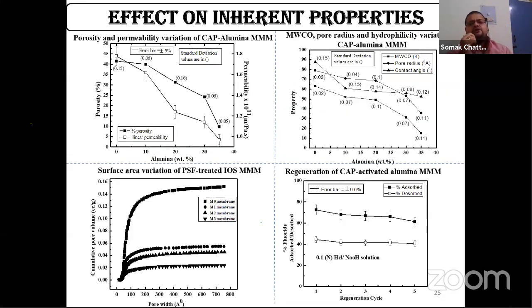Now, different inherent properties were also significantly impacted. One of these was the porosity and permeability. As we discussed on the SEM image, the continuity of the pores gets decreased. And since the continuity of the pores gets decreased, we have a severe reduction in porosity and the permeability of the membrane. This is one of the most important drawbacks of this kind of membrane. So effectively, we need to strike a balance between selectivity and productivity when we are trying to fabricate this type of membrane.